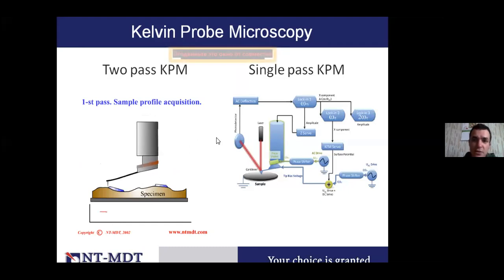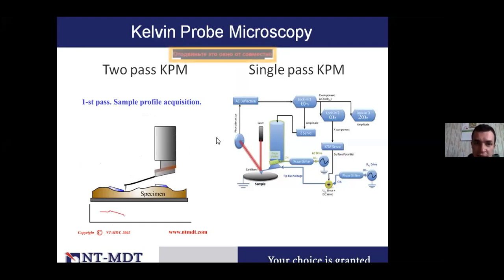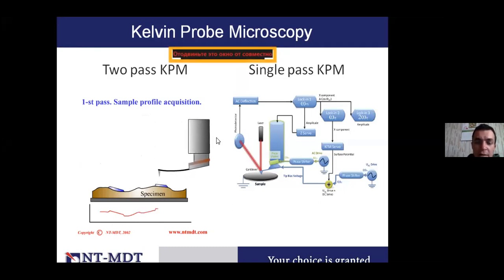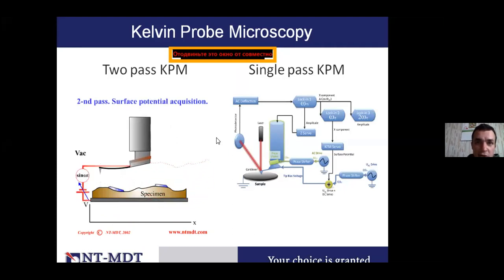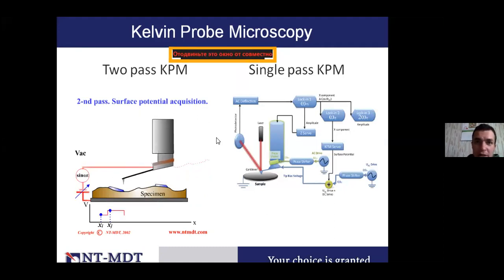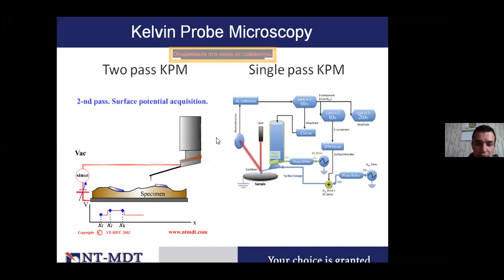Also, an alternative way is to use single pass Kelvin probe microscopy, when we apply the driving voltage for the mechanical oscillation and the driving voltage for electric oscillation at a different frequency. In that case, we can measure topography and the electric properties at the same time without two passes.